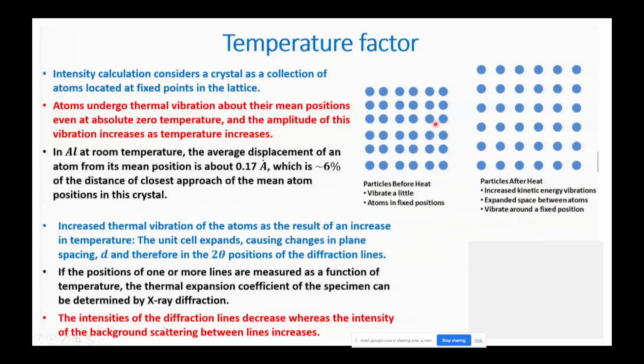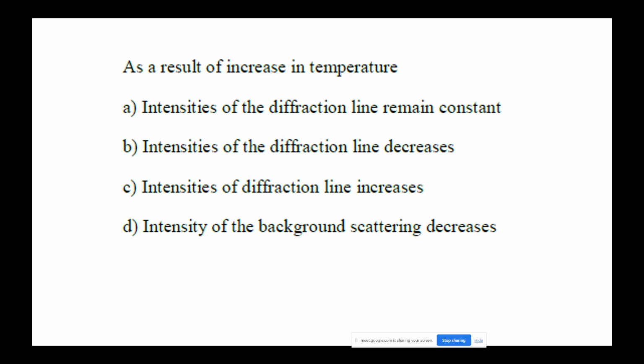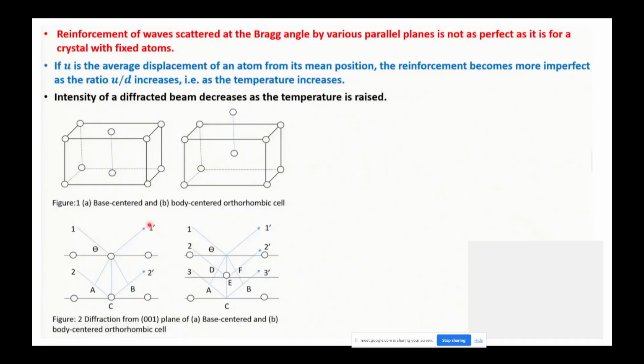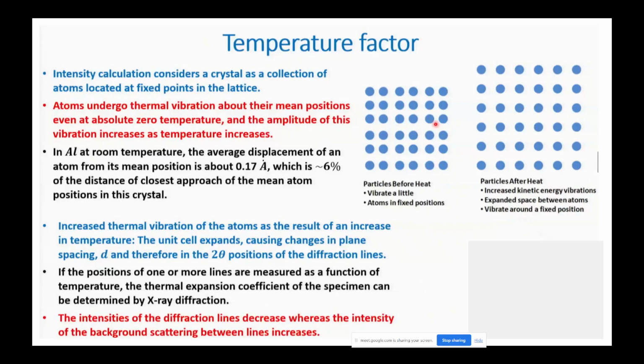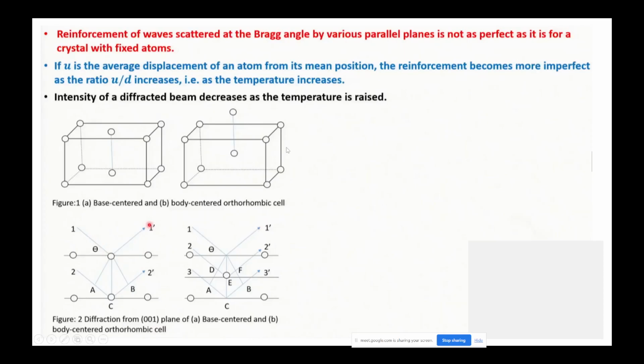So with increase in temperature, the intensities of the diffraction lines decrease, whereas the intensity of the background scattering between lines increases. So it is asking about the intensity of the diffraction line, which will decrease. So the option will be B, not A. You can see in the slides the explanations: the particles before and after heating gain kinetic energy, vibration, expanded space between the atoms, and vibrate around the fixed position. So before heat and after heat, when we increase the temperature, the diffraction line decreases. So the intensity of a diffracted beam decreases as the temperature increases.